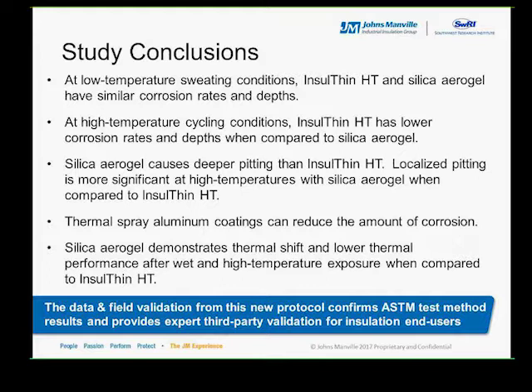And finally, from an insulation manufacturer standpoint, one of the important learnings for us from this study was the conclusion that there's pretty good correlation between the laboratory scale testing that we've been doing that are on our data pages, the C1617 and C665, and the system testing, again, that we just described here in the NACE TG516. And even more critical, as Leo described, that there's pretty good agreement between the NACE test method and field conditions as seen by ExxonMobil and the collaboration with them.